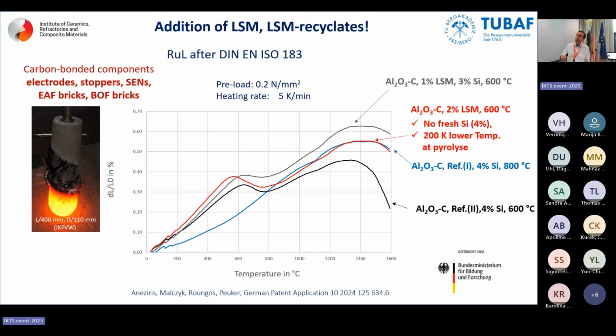And somebody would say, how do you mean it in means of refractories? I can add it in a carbon bonded electrode system or a stopper or whatever. And what we see here is the refractoriness under load. The red one is a carbon bonded alumina with 2% recycled lanthanum strontium manganate. And the blue curve is the traditional carbon bonded alumina with 30% approximately, plus antioxidants in means of something like 4% silicon.